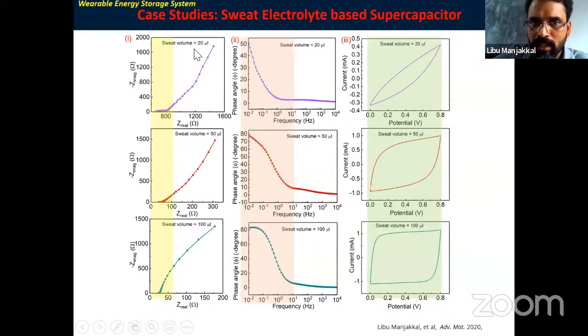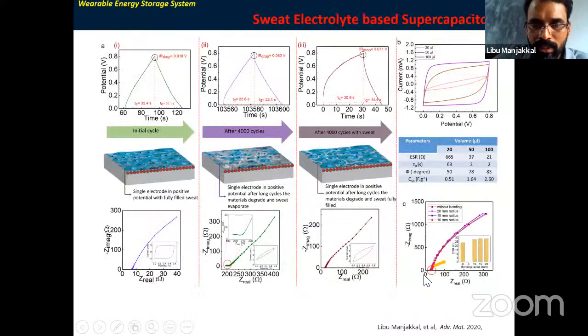And you can see here 20 microliter, and also 50 microliter and 100 microliter. You can see that at 100 microliter, depending on the size of the electrode, it shows almost a rectangular shape in performance and a high energy density area. In addition to this, human sweat on a cloth can easily evaporate. Then I did a continuous cycle study. In the initial cycles, the charging and discharging performance is almost the same.